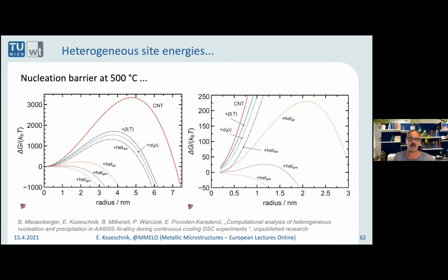Yeah, and then I went ahead and calculated the nucleation barrier at 500 Celsius. And this is the 3000 kBT, which I was indicating before. The red line is classical nucleation theory, and that will predict this high barrier, which will absolutely avoid any precipitation. Now, what happens if we add, let's say, the temperature effects? This plus beta means this is the diffuse interface effect. That will reduce substantially already the barrier, but it's still too high.